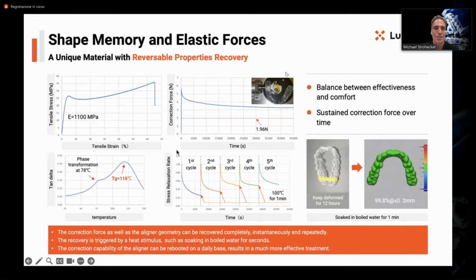The other part of this, which is a key benefit of the direct print aligner versus a thermoform, is that a thermoform material is a thermoplastic. Thermoplastic means you can heat it up and stretch it over your teeth, which is necessary to create an aligner. What thermoset means is what we do. We print an aligner with a thermoset acrylic, which means it's cross-linked. Cross-linking means you have these polymer chains crossing and linking and creating these amazing material properties. And once it is cross-linked and in the accurate shape, if it goes out of shape, there is a way to bring it back.